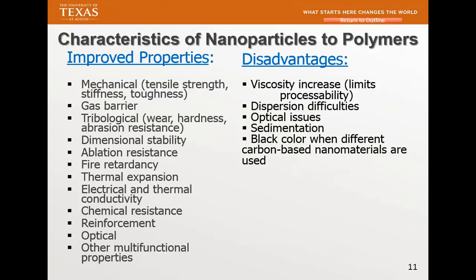The same thing works for thermoplastic. You put it in the twin screw, and suddenly, Dr. Kathy talked to me the day before, and he's putting all these in there, and the machine is not cranking because it creates a lot of torque. It may break the twin screw. So that's what you see in some of these, what you call viscosity increase. If viscosity increases so high, you cannot even turn the twin screw. You may break the twin screw. And that's what you need to watch out for.